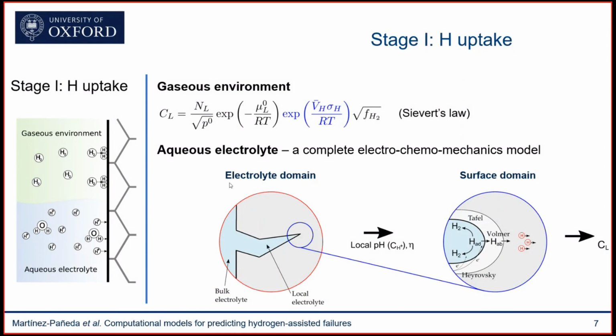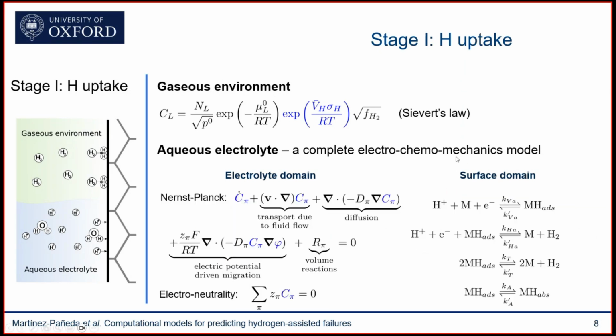However, I think the good news is that we know the differential equations that describe the physics of the electrochemistry of electrolytes, and we know the equations that describe the hydrogen evolution reactions, the Tafel-Volmer-Heyrovsky and absorption reactions. So we can formulate a theory and then implement that theory into a finite element context and obtain predictions. In this case, what you need to solve is the electrochemistry of electrolytes. That means the Nernst-Planck equation and the electroneutrality condition, for every ionic species that is relevant to your system. And then you need to solve for the Volmer-Heyrovsky, Tafel, and absorption reactions near the surface.